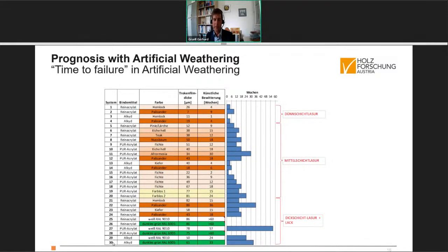We've done a study with 30 different commercial wood coating systems on spruce wood, where we measured the time to failure in artificial weathering. And this is weeks in artificial weathering. And we did the artificial weathering test up to 60 weeks, which is 10,080 hours, which is more than 1 year of continuous artificial weathering test. And you see that many systems were degraded to the limit state maintenance interval up to 30 weeks in artificial weathering.